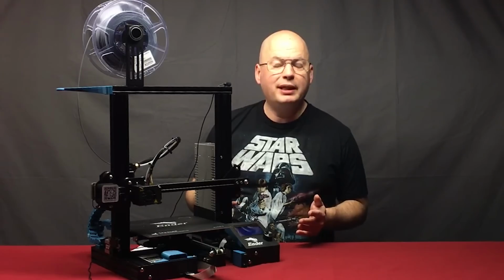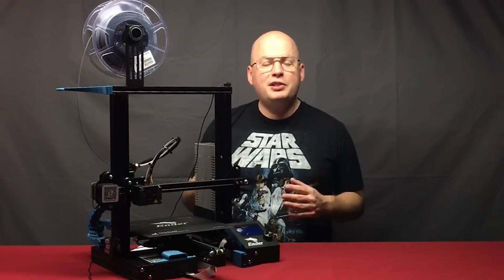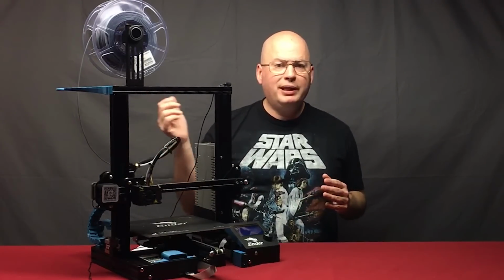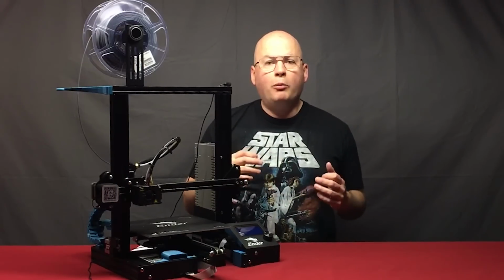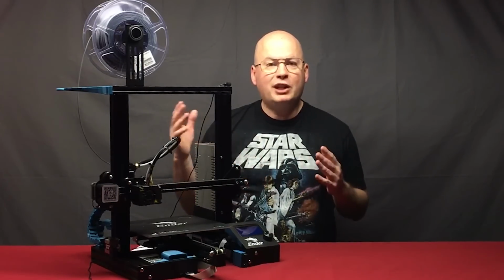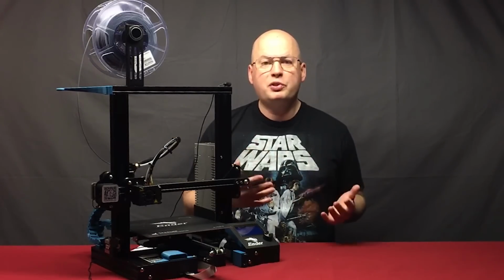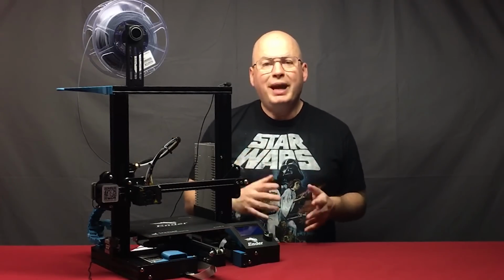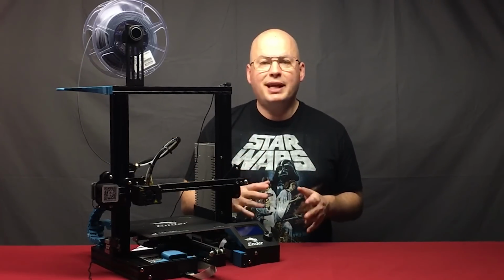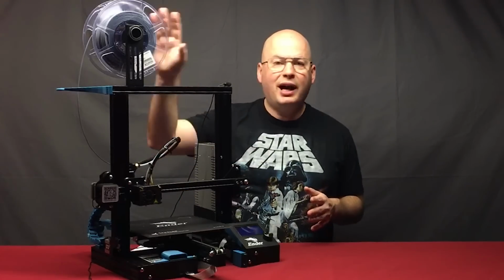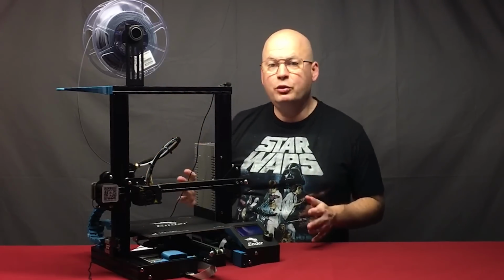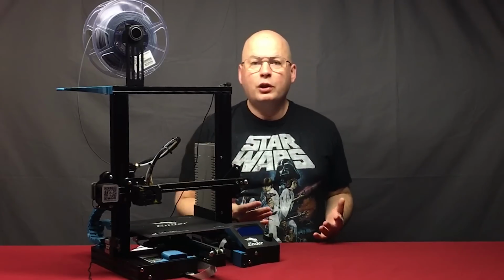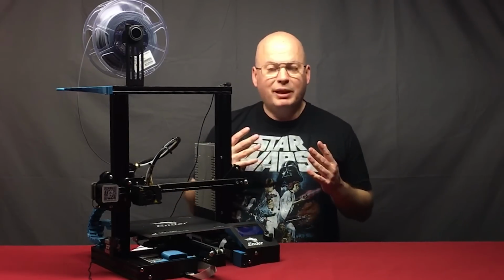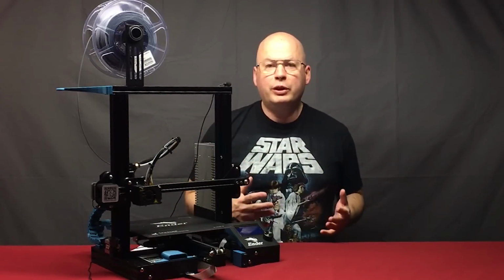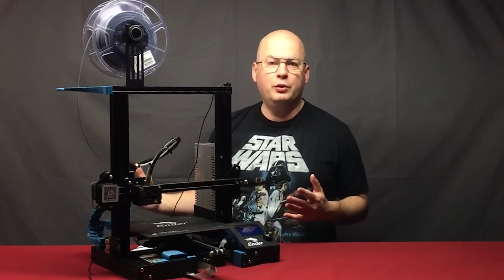1.75 millimeter filament. This caused the slicer to think for every millimeter of filament that was being pushed through the system, almost a third more filament was actually being gone through than what was, which resulted in underextrusion. So make sure your slicer filament settings, the diameter you have set, matches the diameter of filament that your printer actually uses. Again, it's really easy to overlook this, and you can get really frustrated looking for a mechanical issue when in fact it's a software issue.